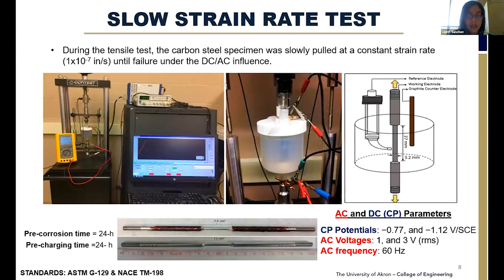So this is an experimental setup. In one of the setups that I use, we use a tensile machine to apply a slow strain rate test, in which the samples that I use are round cross-section bars, like you see here in these pictures, which are slowly pulled at a constant strain rate, in this case 10 to the minus 7, until failure.